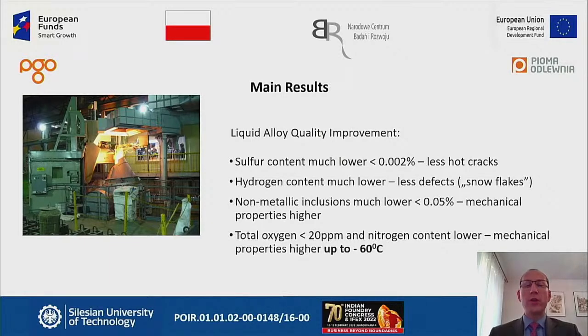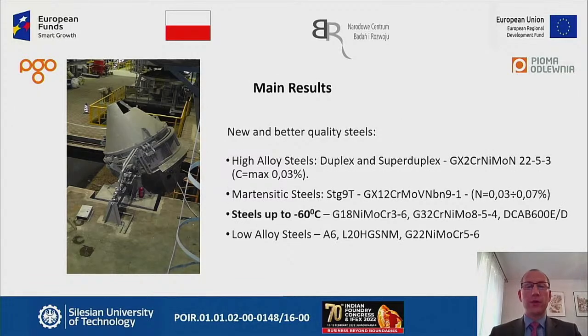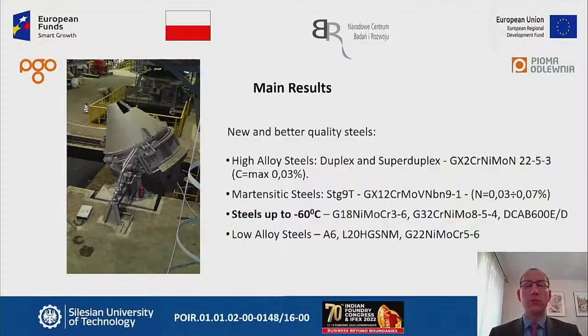because of the very low level of non-metallic inclusions in the percentage of the surface of the tested samples. And because the total oxygen is very low and nitrogen is very low, we can achieve higher mechanical properties, down to minus 60 centigrade, which was the main goal of this project. So here you have only a few examples of the new steels, of the new alloys we could implement into the manufacturing routine of the steel plant.